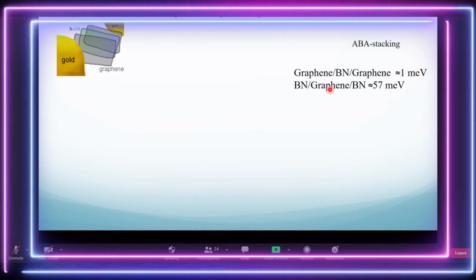But for the case when graphene is sandwiched between boron nitride on both ends, which you expect because it provides a dissimilar electronic configuration or polarization to these carbon atoms in the carbon lattice, a gap opens up pretty high, about 57 meV. And as you tell the experimentalists, they say, well, that's fine, but can you do some transport characteristics so we can see how this gap reflects in IV characteristics.